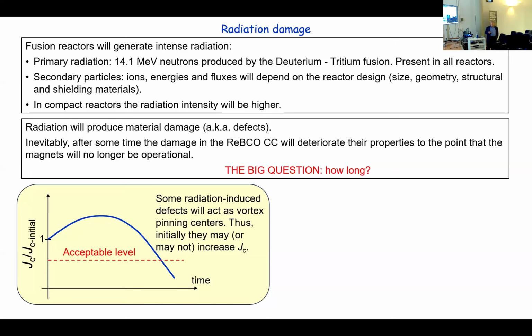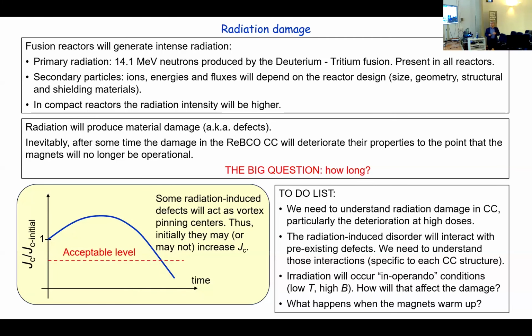So some of the radiation-induced defects will act as vortex pinning centers, and then will initially increase the JC for the reason that I explained before. May or may not, depending on the characteristics. But for sure, they will deteriorate JC at some point. As a function of time, there will perhaps be an initial increase, and then a deterioration, and then at some point it will go below the acceptable level. And this is what we need to understand.